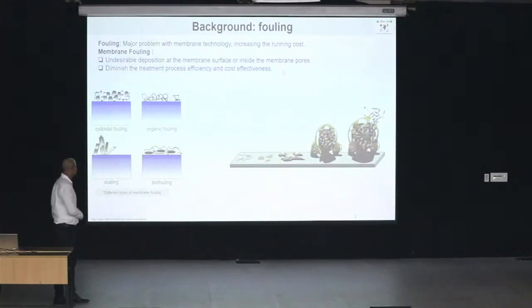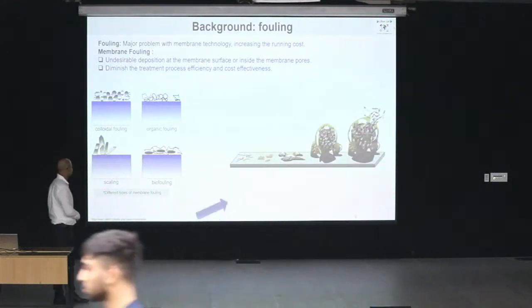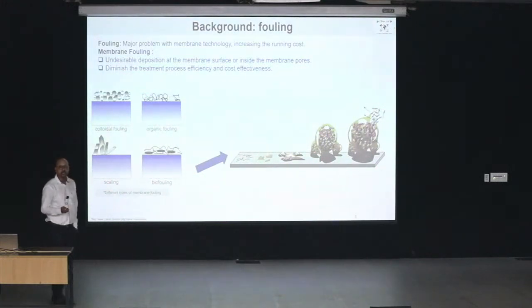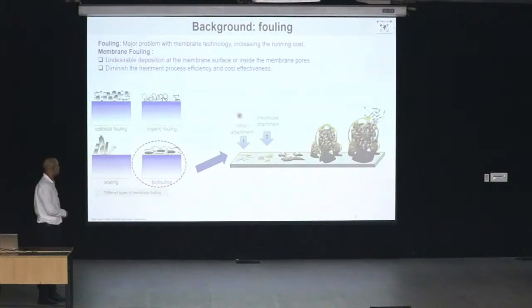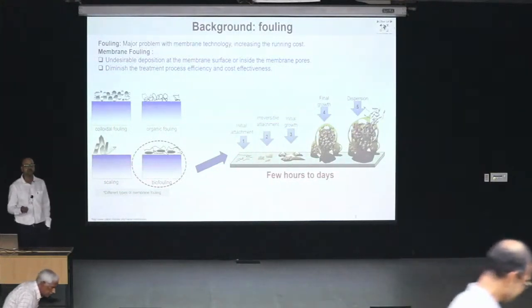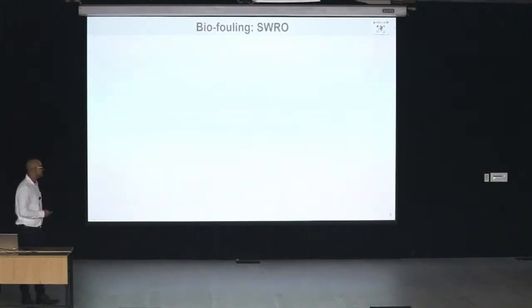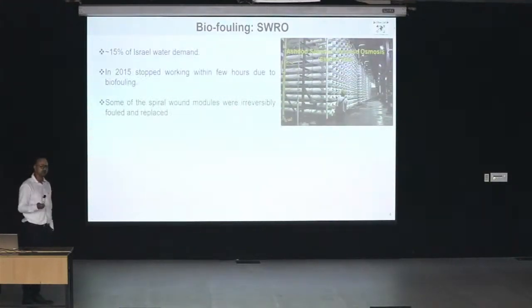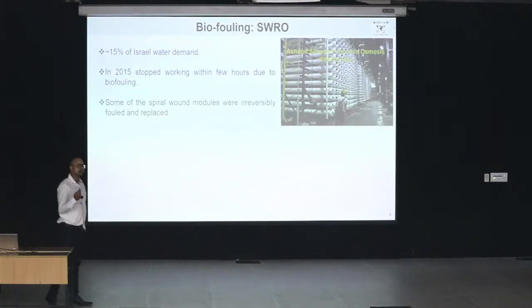And out of these, biofouling is the worst one, because here living microorganisms are involved, and what they do is first attach to the surfaces and then start forming their colonies, and after different stages, when they are fully grown, they can go away and contaminate other places in the membrane. And interestingly, according to your environmental conditions, this whole process can happen within a few hours to a few days. And this has created a lot of problems when we are running very big plants.